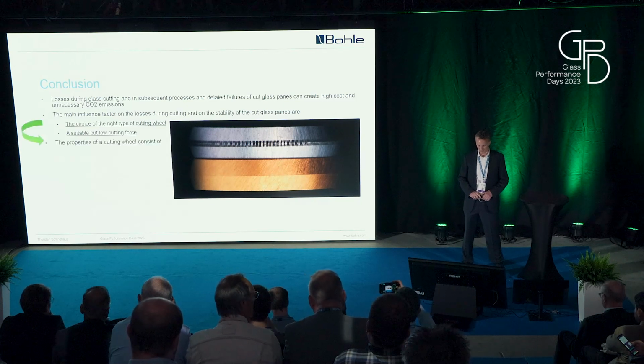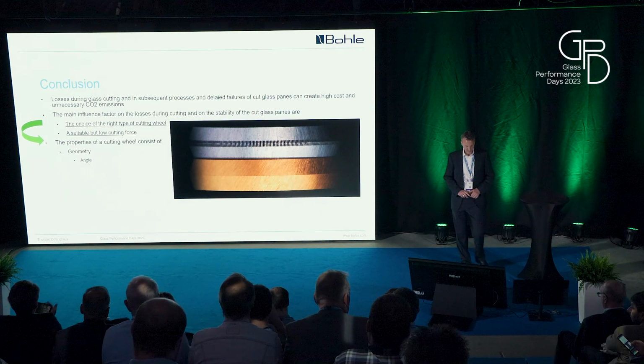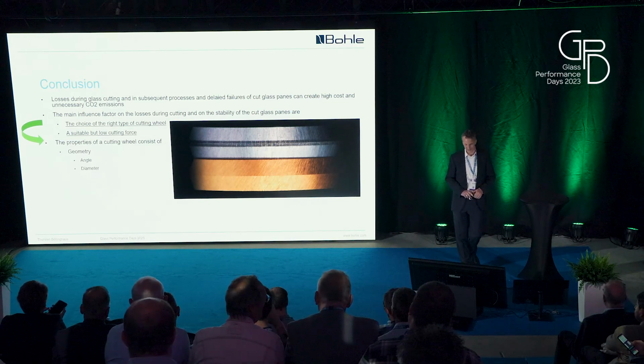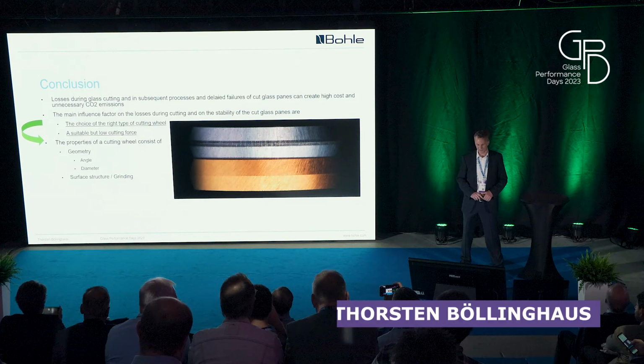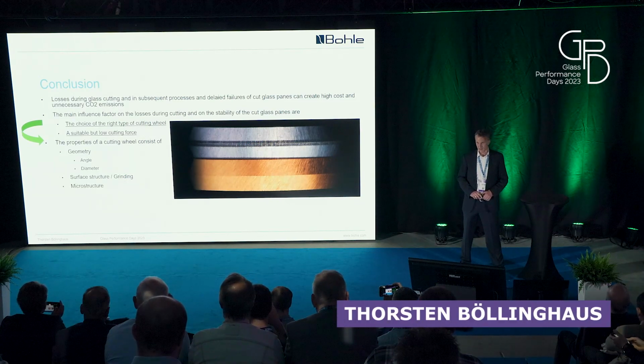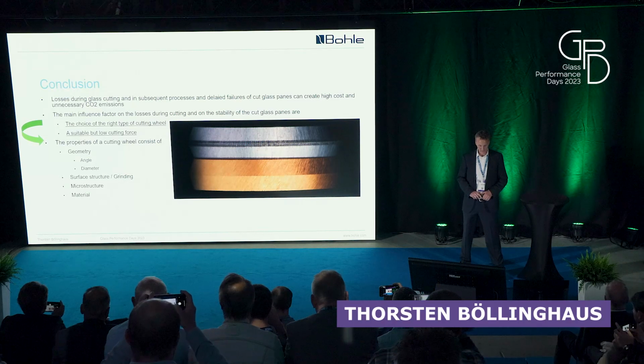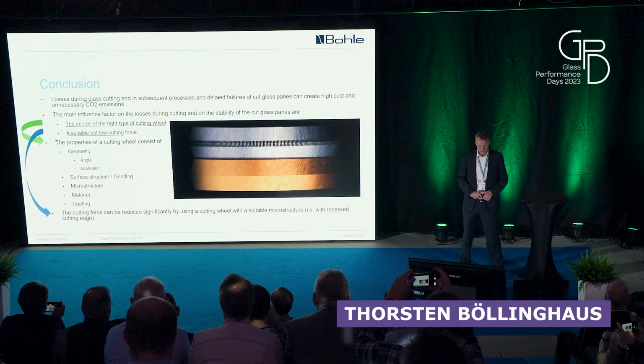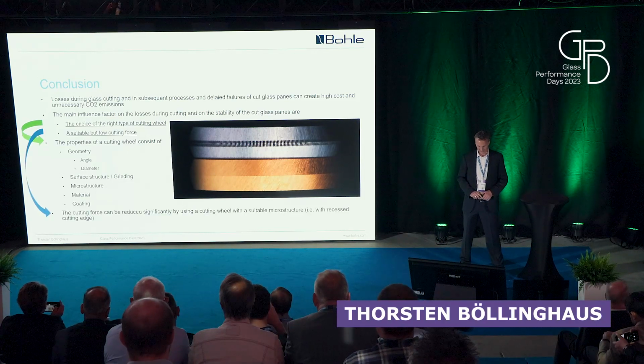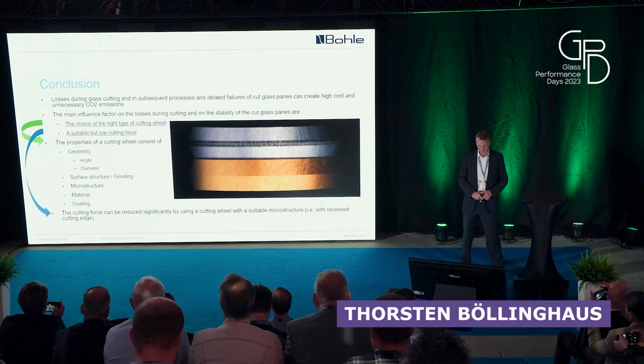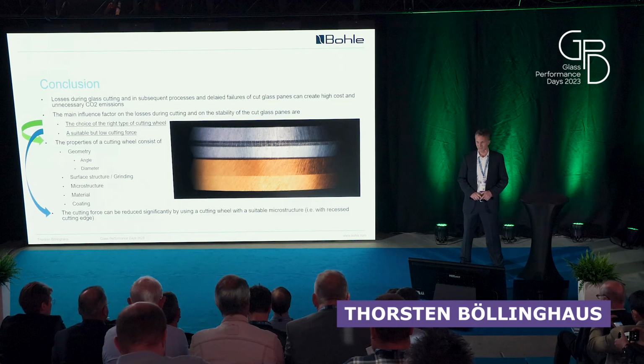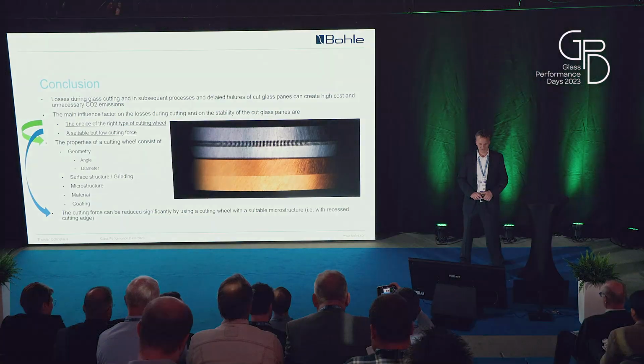Regarding the choice of cutting wheels, you have to take the right angle, for instance, and the right diameter. You have to take the right surface structure and the right grinding microstructure if applicable, and if necessary, the right material and a coating, while respecting a suitable but low cutting force. One way, apart from choosing the right cutting wheel, is then using a microstructure with recessed cutting edge. So this is it. I hope this was interesting to you, and I'm very open to questions from the audience.